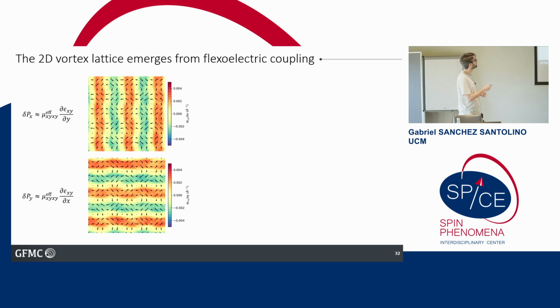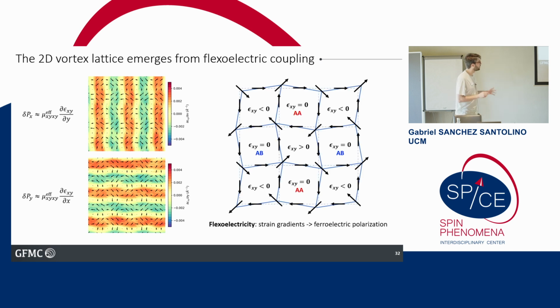So you get the gradient of the strain, it gives you these kind of stripes, and if you look at the arrows, which are the ferroelectric polarization, for a positive gradient of the shear strain we are going to have arrows pointing up, and for a negative gradient, arrows pointing down. So the gradient of the strain is going to pin our ferroelectric polarization, and the same happens for the other direction. For the positive shear strain gradient, the arrows point right, for the negative one, the arrows point left, and this is pinning the polarization. And this is the final view. We have this diagram with a lattice of positive and negative shear strain cores that pin our polarization and create these ferroelectric vortices.